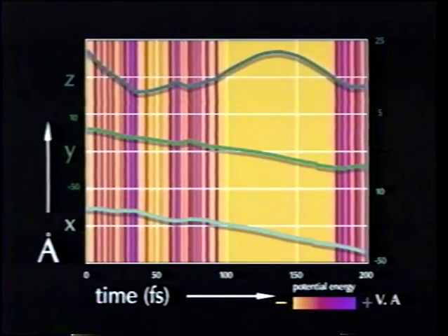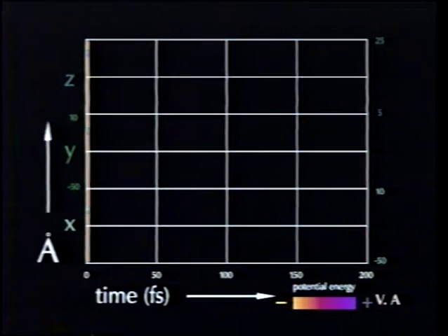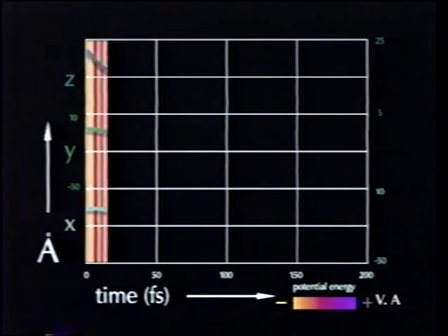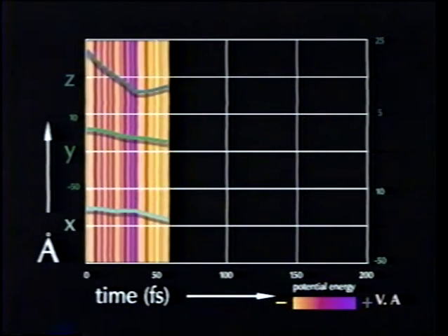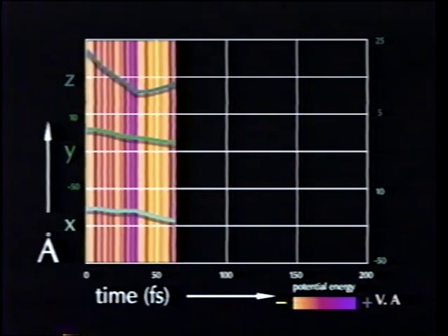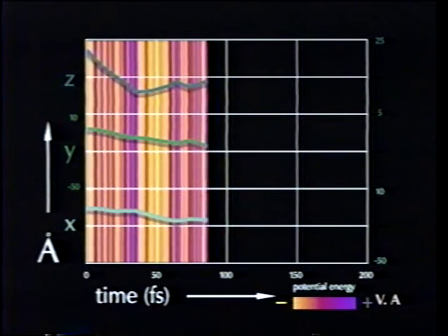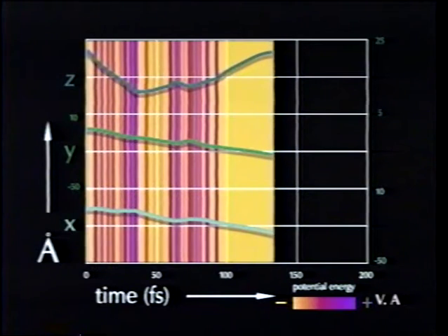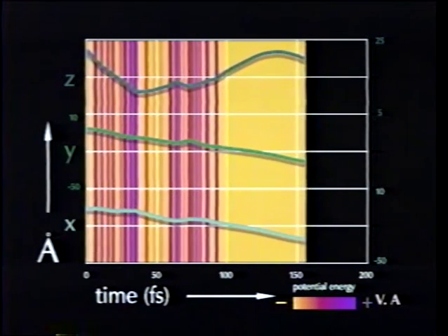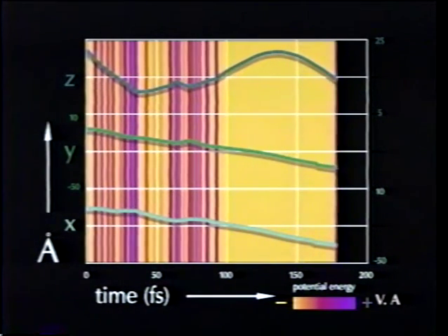This plot of the hydrogen atom's position and potential energy shows the huge number of collisions which occur. The first quiescent period, from 45 to 55 femtoseconds, is the period of nearly horizontal motion just under the first layer before the atom doubles back on itself. The period between 95 and 180 femtoseconds is the hydrogen atom's excursion over the hill and back down the other side.